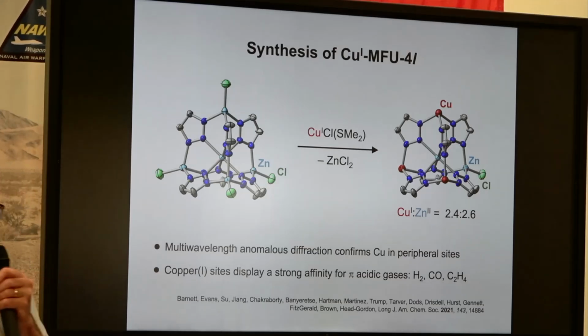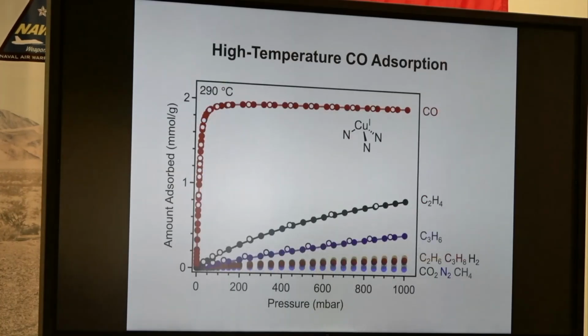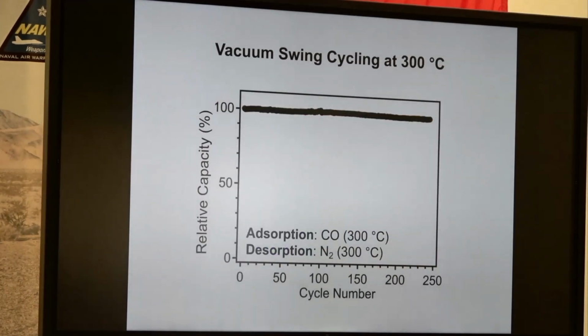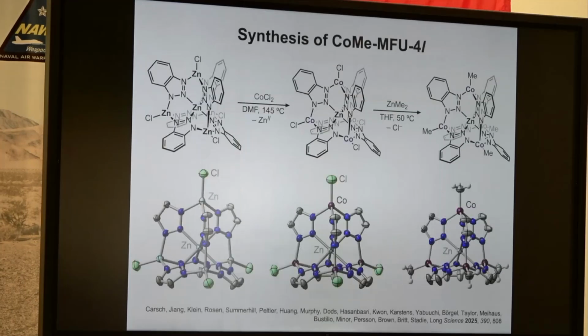Sadly, we can only get about 2 to 3 of these coppers exchanged in this reaction, instead of all 4 of the peripheral sites. But this material now binds CO at very high temperatures, near 300 degrees C here. And you can see it's reversible just with vacuum swing. It also has an appreciable affinity for ethylene. You can see ethylene is the next steepest isotherm, which is also very difficult at these temperatures. Okay, and you can adsorb and desorb using a vacuum swing.